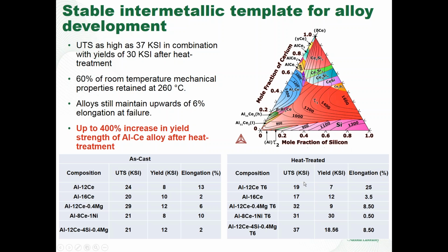And when I talk about heat treat, I'm talking about a typical type of T6 heat treatment where you're heating it up to 1,000 degrees F and then you're quenching it. So they really don't have much of a response. Once you start adding elements, then you get a lot of response to the heat treat, because you end up with more traditional kind of heat treat response. You get a good response in the cerium nickel series. There's a lot of work that has to be done on heat treat on some of the alloys, particularly that are not primarily magnesium alloys.